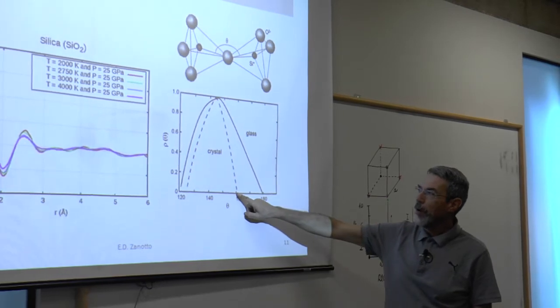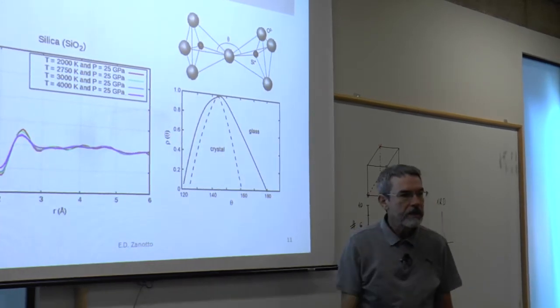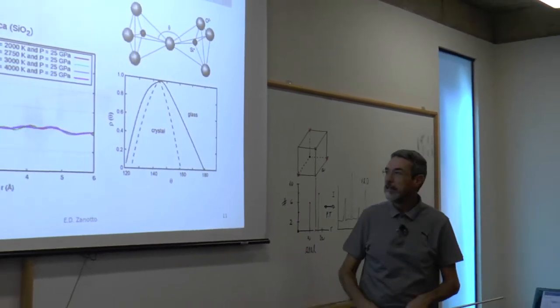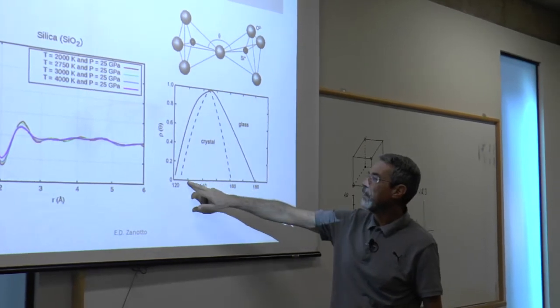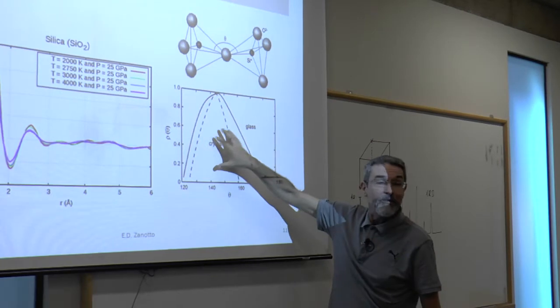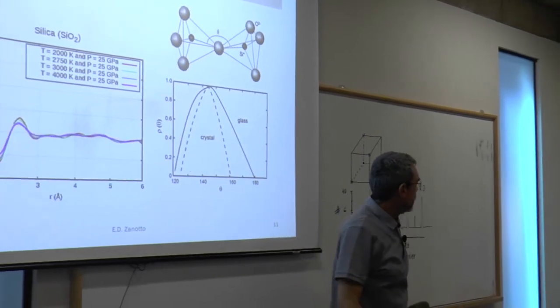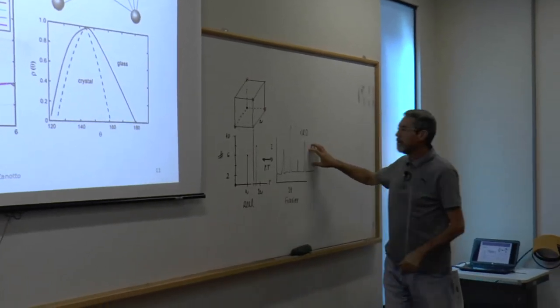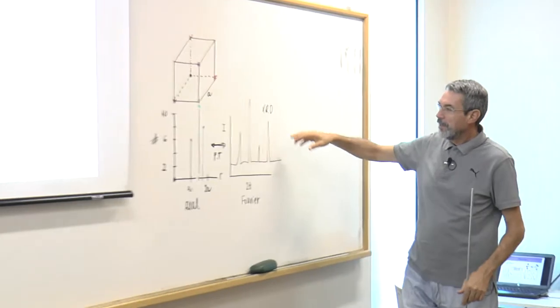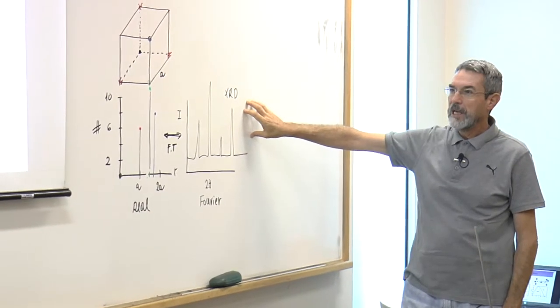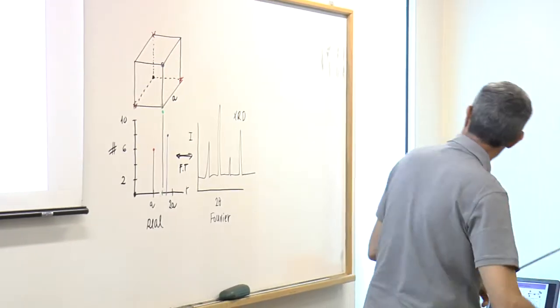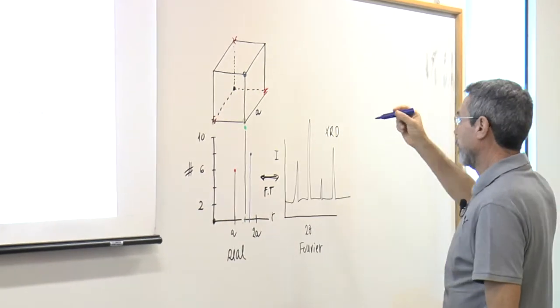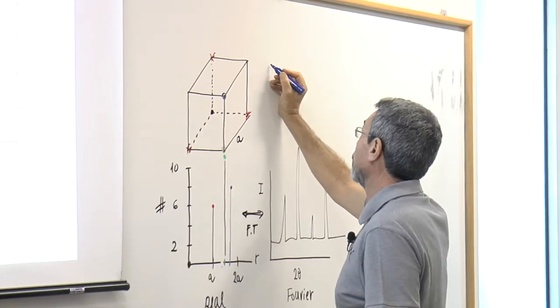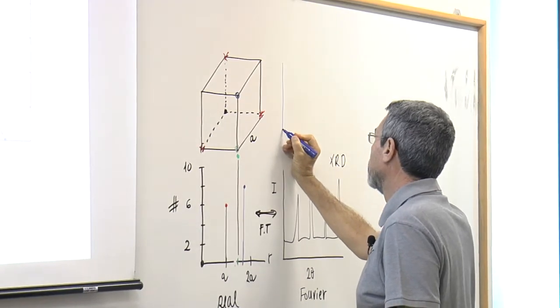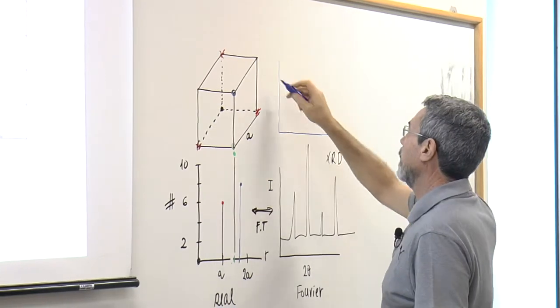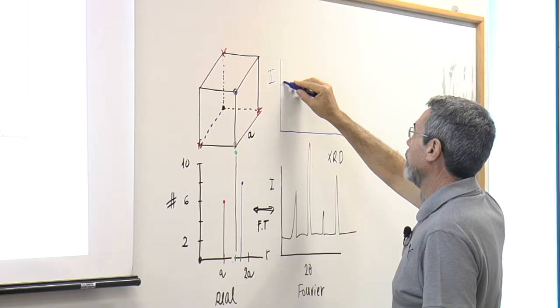Whereas the crystal also is not perfect. This is a real crystal, and a real crystal is not completely perfect, a crystallite in this case. The angles vary from 130 to 160. This difference here is enough to give very sharp peaks in an XRD experiment for the crystal and very shallow peaks for the glass. So if we did here the XRD spectrum for glass, the intensity versus 2 theta, that's what we get.